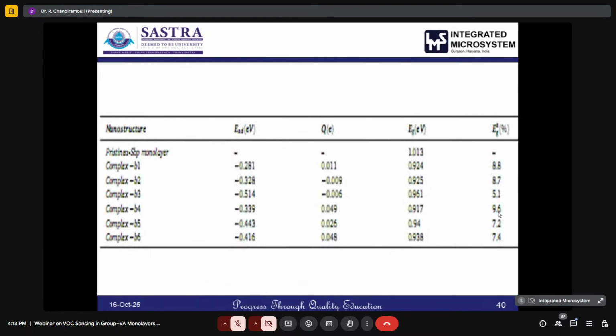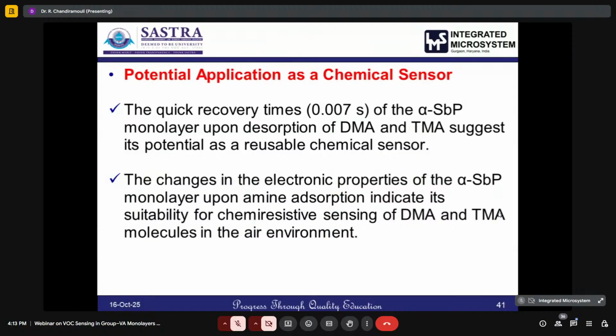In all this work, the main factors are the adsorption energy, the Mulliken charge transfer, and the energy band gap, and the average or relative energy band gap variation is explored and reported for the adsorption studies, along with the potential application as a chemical sensor. This material, alpha SbP, has a quick recovery time, and the alpha SbP monolayer upon desorption of DMA and TMA molecules suggests a reusable chemical sensor. The changes in the electronic property of the alpha SbP monolayer indicate its suitability for chemiresistive sensing of DMA and TMA molecules in the air atmosphere.